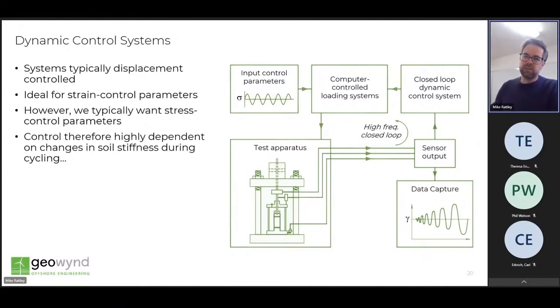A good portion of the cyclic test systems used by commercial laboratories are actually displacement control systems. It's important because that fact makes them ideal for strain control tests, where they can produce almost textbook quality results, since the input control parameters are the same as the load system control parameter, i.e. it's displacement, and the control feedback loop is somewhat direct. However, as we've mentioned earlier and as described by Carl, the requirements of cyclic analysis of offshore foundation typically means that we need stress control testing to calibrate and to provide input to the models.